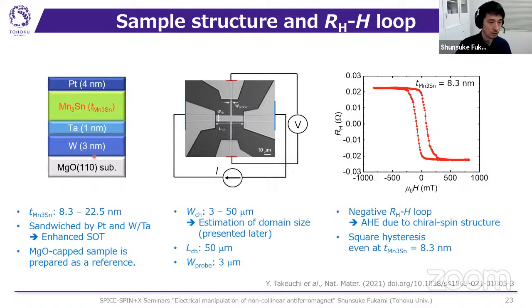This shows the stack structure we used to observe the chiral spin rotations, and this shows the optical micrograph image of the fabricated device with the measurement circuit. We prepared a Hall bar device in which the channel width was varied from 3 micrometers to 50 micrometers, and the channel length and the width of the Hall probe were fixed to 50 micrometers and 3 micrometers respectively. This shows the Hall resistance as a function of the magnetic field, which was applied along the perpendicular out-of-plane direction, for the Mn3Sn thickness of 8.3 nanometers. A very nice negative and square RH loop was observed, which means that the anomalous Hall effect due to the chiral spin structure is observed.